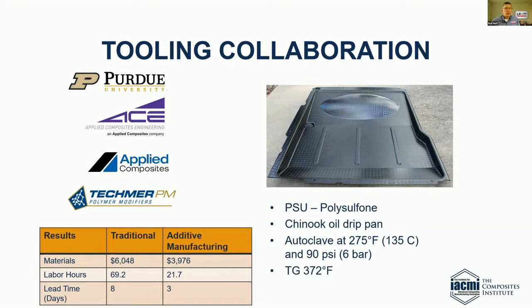The labor hours were reduced from just over 69 to under 22 hours, and the lead time went from 8 days to 3 days by implementing additive manufacturing. By the way, they let this tool ride in the back of their autoclave for months so that it got through a lot of cycles, and it never degraded as far as we could tell.